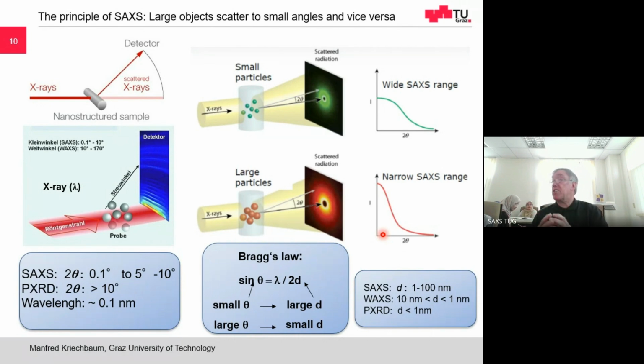With powder X-ray diffraction, this is wide angle. You're studying atomic distances. But we are more interested in nanostructure or nanostructural assembly of molecules. So our range is, I would say, from 1 to 100 nanometer. So it means our angular range is, if we're taking a wavelength of 1 angstrom, about 0 to 10 degrees. So all our information is between 0 and 10 degrees. This is the small angle X-ray scattering range.